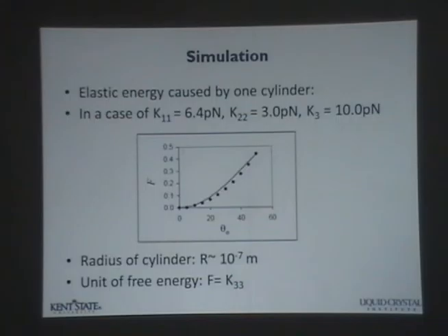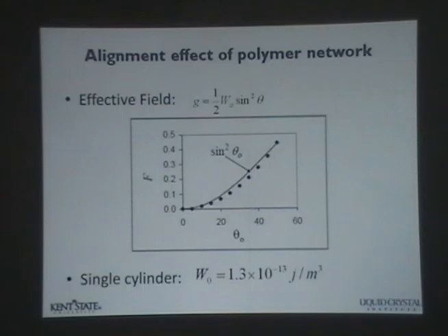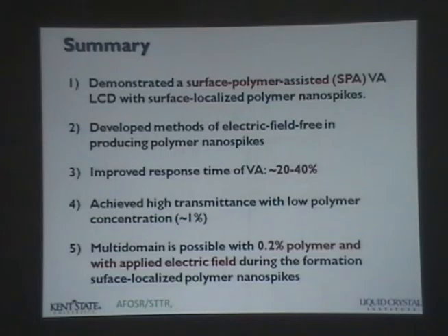From this, you can estimate the effective anchoring field. In ideal conditions for a single cylinder, you can estimate how much anchoring the liquid crystal experiences nearby those polymer spikes. You can use simulation to study whether that effect matches your experimental claim. Improvements of response time range from 20 to 40% achieved with 1% polymer. If you want high light transmission — important for the display industry, because you want to drive the image with low energy to the backlight — that is also important for mobile devices.